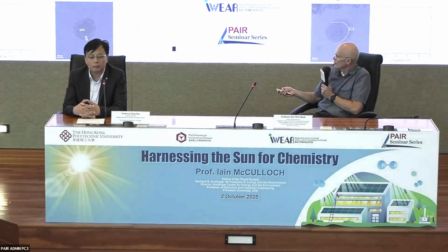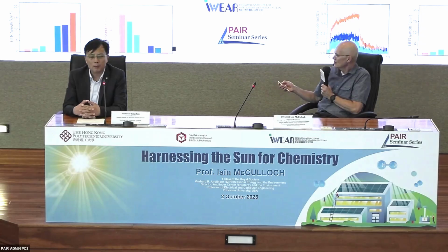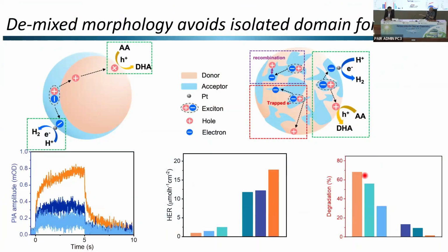Well, the first thing is to really identify what we mean by instability. When I show a slide like this one, it doesn't really help. Degradation 60, 70%. What do we mean by degradation? What we're saying here is that this is UV absorption data, so 70% of the absorption or the extinction coefficient is gone. But where has it gone and what has happened? I think we need to understand, firstly, what the sources of this instability are. Is it just material fragmentation? Is it photobleaching? Is there actual chemistry going on? We're trying to do this now.